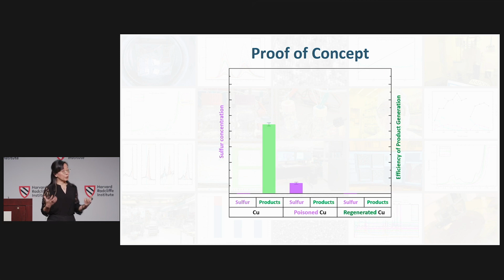How much we produce from a clean copper surface is our baseline. We have to benchmark against this to know what effect we have when we poison and when we clean the copper. Okay, so that's our starting point. After we poison the surface, that green bar dropped to essentially 0, very, very low. It did not go to 0 because we used a model compound. We didn't use the flue gas. But the effect is clear. The sulfur poisoned the catalyst, and we cannot use it effectively to produce the products.